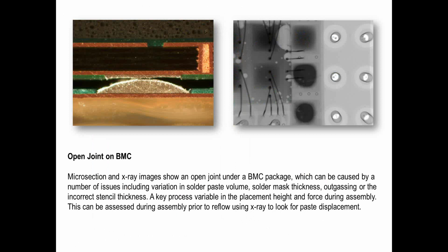Now open connections are probably one of our biggest problems. If we've got shorts on most components, not all, it's a fairly minor thing to remove. Obviously shorts underneath BGA or LGA packages, but opens or intermittent joints can be an issue. And one of the important things you've got to try and learn is when we're looking at X-ray to try and understand whether we've got a joint or whether it's actually an open. So what I've done here is put 2 side by side, and you should be able to interpret from what I'm showing you the difference between the joints.